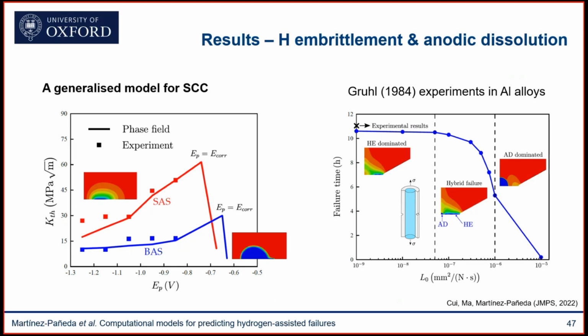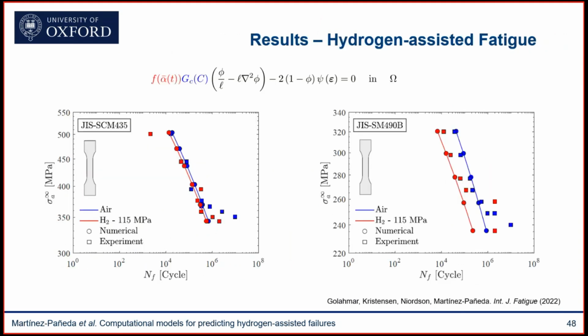We don't need to say a priori, okay, it's going to be hydrogen embrittlement, it's going to be anodic dissolution. We just run our model, we provide environmental conditions, and let the model pick which mechanism is going to be dominant. And that allows us to deliver predictions over a wide range of applied potentials. So for any choice of environment, you can see here that we go from the cathodic regime where hydrogen embrittlement dominates to the anodic regime where anodic dissolution dominates. And we can also capture the interplay between the two. This is, for example, a representation of the classic experiments by Gruhl on aluminum alloys where he was trying to understand the interplay between hydrogen embrittlement and anodic dissolution.